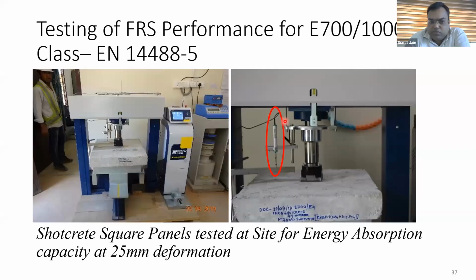This was the apparatus which we had on the site, and we were testing panels right at the site for all the pre-construction and production controls. This was tested as per the European norm EN 14488-5. On the right side of the image, this is the LVDT, which measures the displacement of the panel. And this is the central plunger, 100 by 100 mm, which loads the specimen at the center.